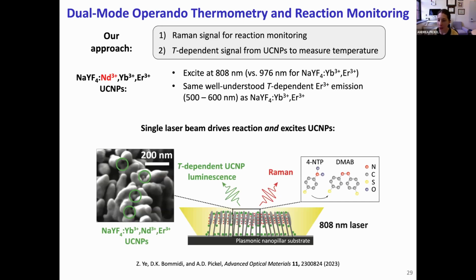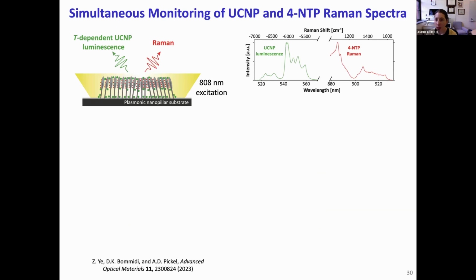Because the UCNP emission is shifted all the way into the visible range, while the Raman signal remains much closer to the excitation wavelength, these two signals naturally separate in the spectral domain, which I'll show in just a moment. And we use the photocatalyzed dimerization of 4-nitrothiophenol, or 4-NTP, to dimercaptoazobenzene, or DMAB, as a model reaction. So when we excite our samples with the 808 nanometer laser, we see, first of all, as I mentioned just a moment ago, that the UCNP and the 4-NTP Raman spectra naturally separate in the spectral domain.